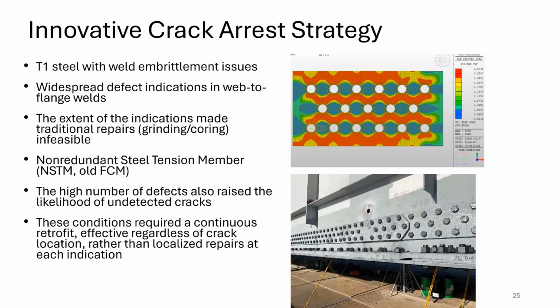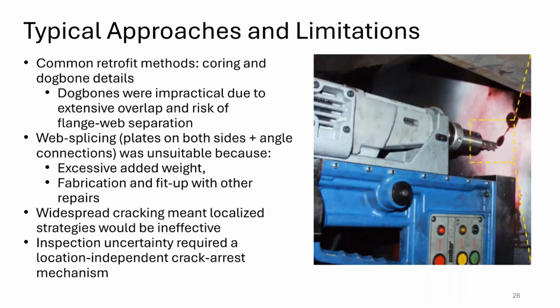So when we encounter this kind of web to flange weld issue, the typical approaches are either based on coring methods or the installation of dog bone details. You would typically use a coring method as shown in this picture when you have already detected a crack extending from these web to flange indications, and then you core out the tip. By that, you reduce the stress intensity at the crack tip, and therefore you now have a blunt crack that doesn't grow.